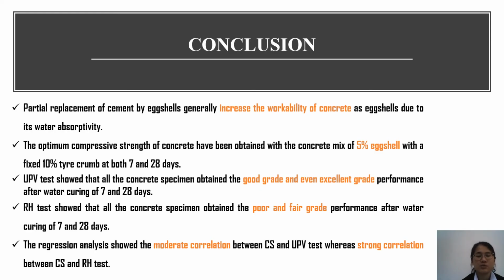Here I can make some conclusions for my research. First of all, partial replacement of cement by eggshell generally increases the workability of concrete due to eggshell's water absorptivity. Secondly, the optimal compressive strength of concrete has been obtained with the concrete mix of 5% eggshell with a fixed 10% tyre crumb at both 7 days and 28 days. UPV tests show that all the concrete specimens obtained the good grade and even excellent grade after water curing of 7 days and 28 days. Whereas rebound hammer tests show that all the concrete specimens obtained the poor and fair grade performance after water curing of 7 days and 28 days.